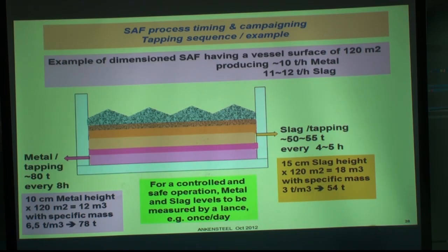And I really would recommend maybe once a day, not very often, to check, because you will have installed a mass balance of the furnace, and the mass balance will predict that having charged X tons, having tapped X ton of metal, having tapped X ton of slag, the model predicts the level of this for metal, this for slag, etc. But it's good once a day to check and to measure and to reset the model. I see. Okay.